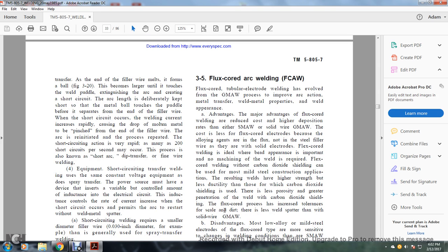3.5 Flux core arc welding, or FCAW. Flux core tubular electrode welding has evolved from the gas metal arc welding process to improve the arc action, metal transfer, weld-metal properties, and weld appearance. Advantages: the main advantages of flux core welding are reduced cost and higher deposition rates than shielded metal arc welding and solid wire gas metal arc welding. These costs are lower because the alloying agents are in the flux, not in the steel filler wire as they are with a solid electrode.